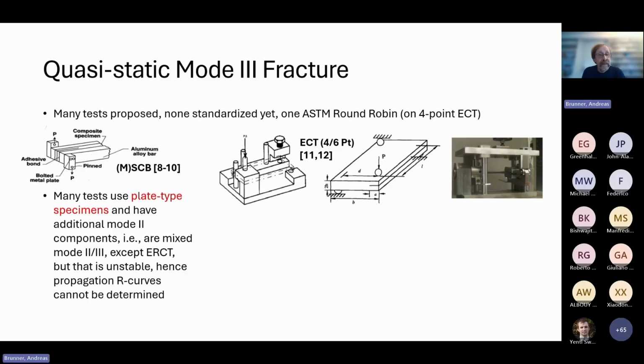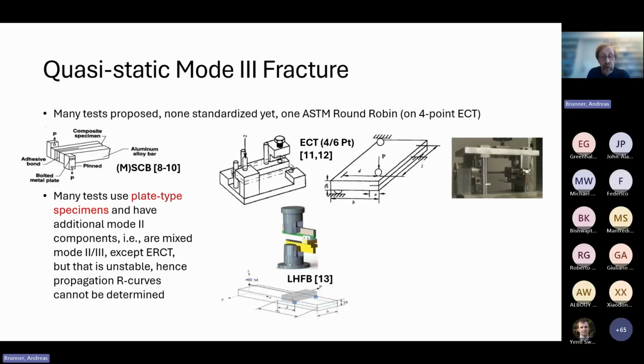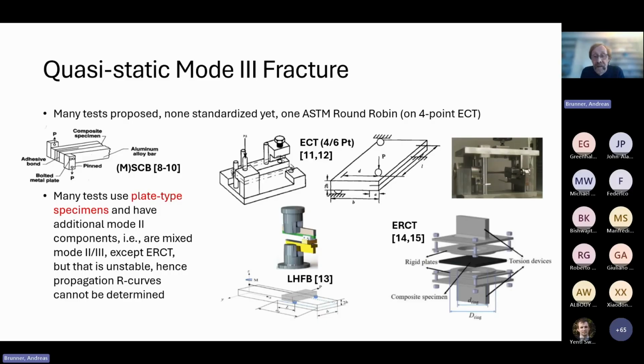And the point I would like to note here is that quite a few of these tests use more or less plate type specimens, but as it has already been said, it's typically additional mode mixity, mostly mode 2 with mode 3. There is an edge ring crack torsion test. The one that is shown here is called longitudinal half-fixed beam, but then the edge ring crack torsion test is shown here. And according to the authors, they say that this is a pure or essentially pure mode 3.